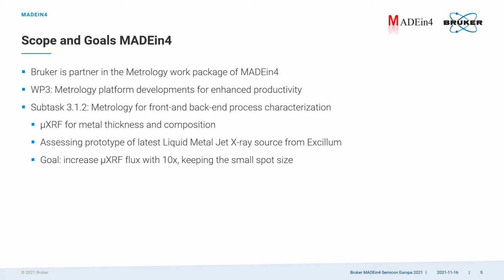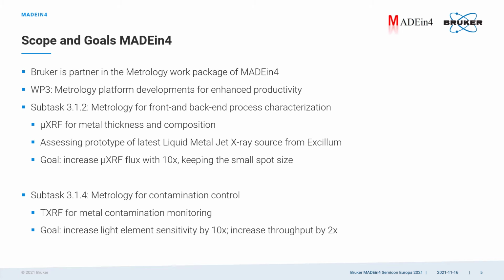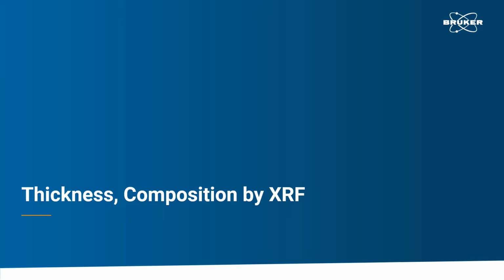The goal we set ourselves in the beginning of the project is to increase the detected micro-XRF flux on known samples by a factor of 10, while keeping the small spot size. The second subtask is focusing on metrology for contamination control. Here we look at TXRF for metal contamination monitoring. The goal was to increase the sensitivity for light element detection by a factor of 10 and to enhance the throughput by a factor of 2, compared to the TXRF tool that was available in the beginning of the project. In the following slides, I'll explain briefly the principle of XRF, and I'll give you examples of how micro-XRF is used in the semiconductor industry.